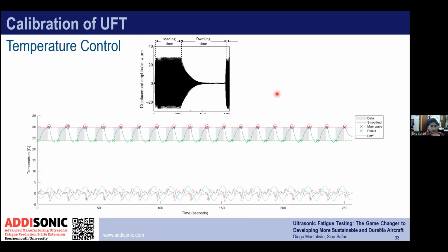So as you can see again in this figure, during the vibration, the figure below shows that the temperature is rising, and then when the vibration stops, the cooling system cools down the specimen to a certain level. We can specify a higher threshold and a lower threshold, so the cooling system can identify when to start and when to stop. And this is what's happening exactly.